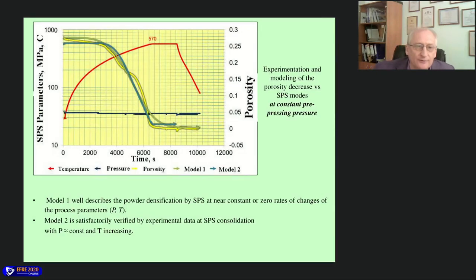Finally, we found the optimal parameters for sintering. This is the heating curve of this composite. Maximal temperature was around 570 degrees C, and in this case our experimental shrinkage of this composite correlated with the theoretical modeling, like model 2 using a logarithmic equation of the consolidation.